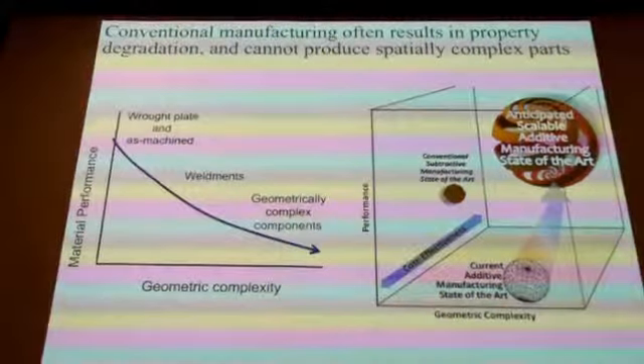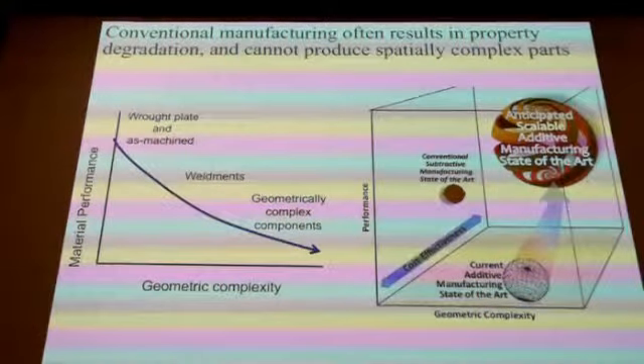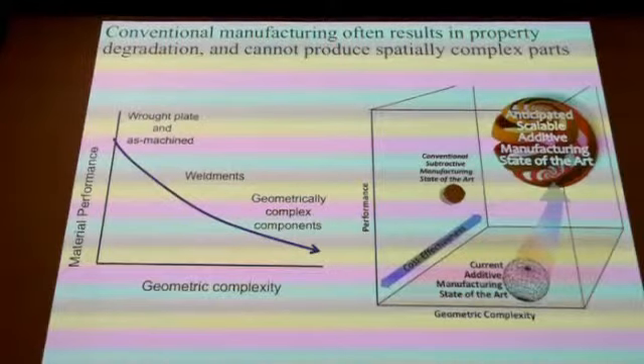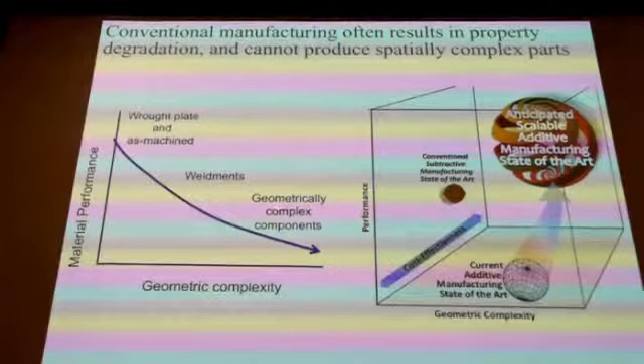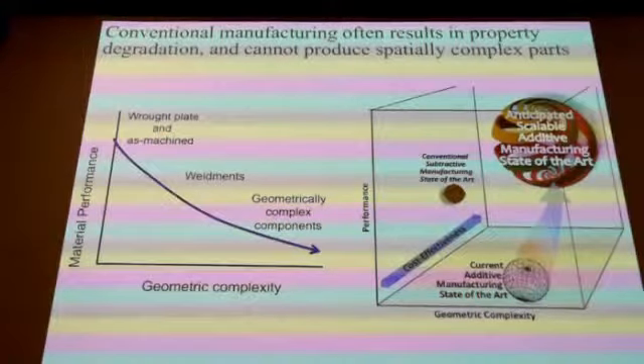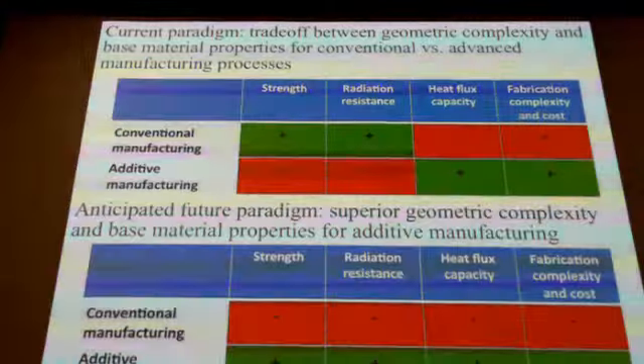So I think with additive manufacturing, there's potential to get significant improvements in the performance of the material along with the geometric complexity while maintaining reasonable costs of the material. Usually as you start to make real world types of materials, you get some degradation as you start to weld the material and as you start to do other fabrication techniques. You tend to get degradation in the performance, but there's possibilities with things like additive manufacturing that you're being able to not sacrifice a lot of the traditional loss of performance that occurs by the conventional techniques.